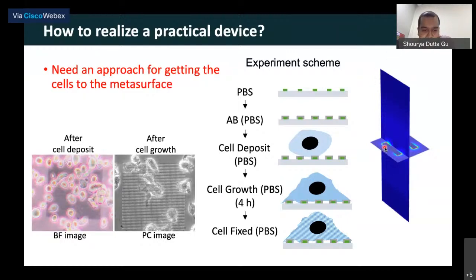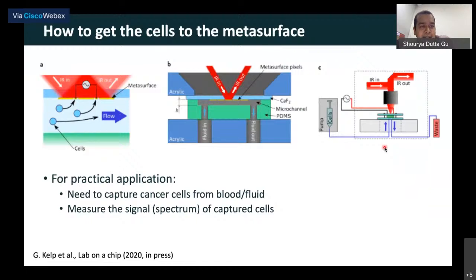For that, we used a technique called dielectrophoresis, or you can use other techniques. But in our case, what we used was dielectrophoresis. What that does is you have a metasurface, you apply an AC electric field, a low frequency electric field, and this field will get the cells to the surface. And then you can do the IR measurement that you would like, and then you can do the classification using principal component analysis.